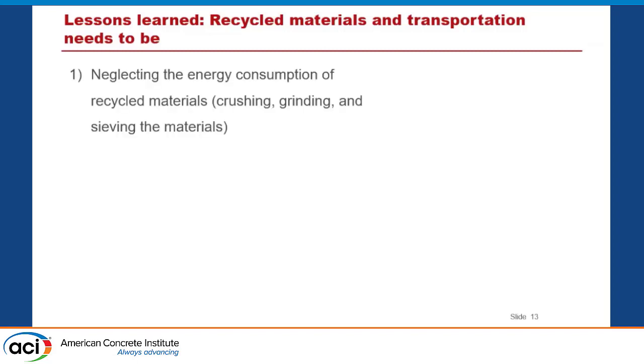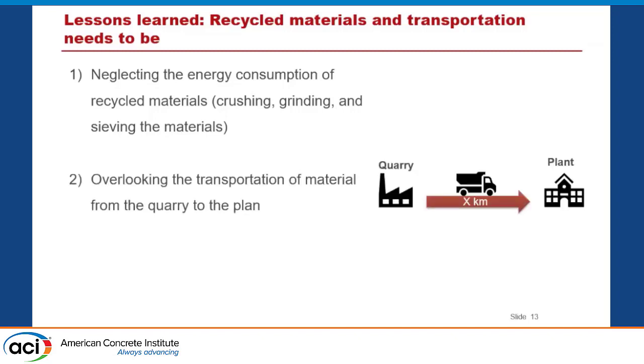From a lifecycle perspective, we learned there were not enough clarifications in the rules. We had to emphasize some important points that students — particularly civil engineering students — didn't consider. First was the energy consumption associated with processing recycled materials. Students notionally consider recycled materials as burden-free or zero-emission, assigning no emissions. But in reality, many materials need post-processing activities — for example, slag needs grinding — so we now emphasize this point in the new version of the competition rules.